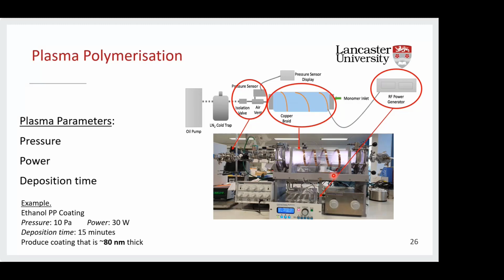The next vital component for the process is then to have an electric field. So to achieve this, we employ an RF generator, and in this case a matching network. And this is connected to a copper coil around your reactor. When you turn this power on, the monomer is then activated, producing this plasma, which you can see in the glow. So power is then the second plasma parameter that we have to control the surface.